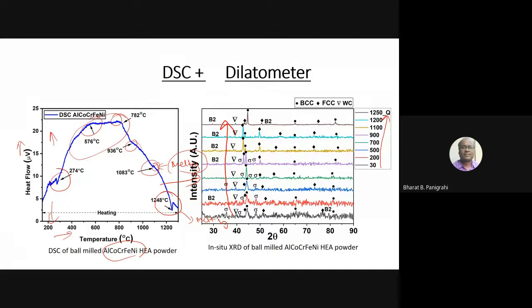I am not going into detail of each peak. What I want to bring to your notice is that with changing temperature, the phases are changing, new phases are forming, some phases are vanishing, some new precipitates are forming. This you can all characterize using the X-ray diffraction, and the corresponding signal at various temperatures you can see using the DSC.